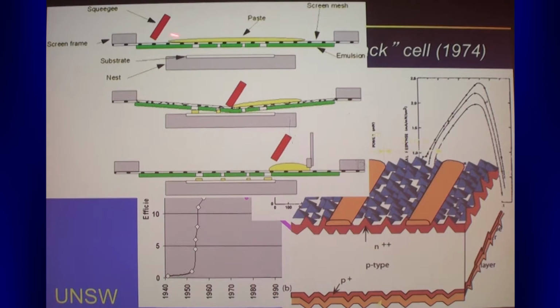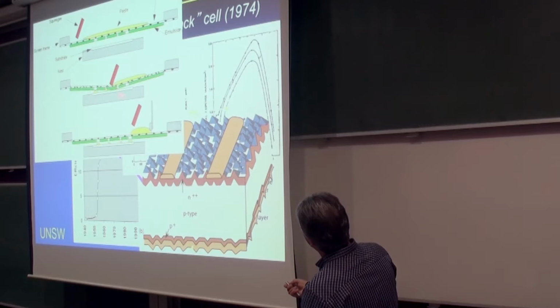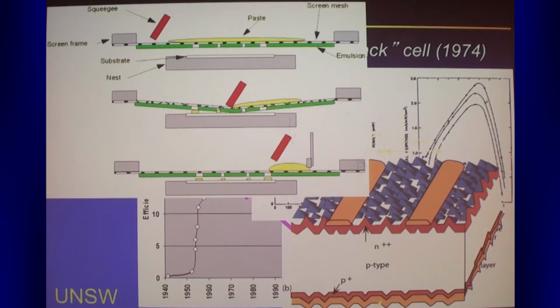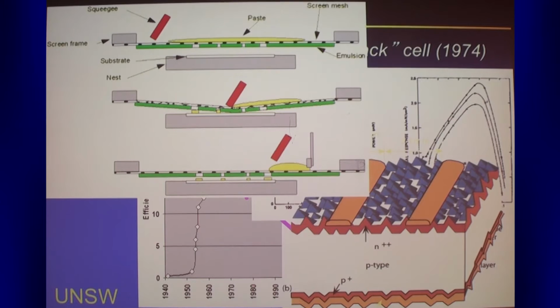You just have this screen and the metal is sort of ground up into a paste, mixed up with other stuff, so that it's a thickish type paste. And then it's just squeezed through this screen onto the cell to give you the defined patterns. The other technique I was talking about last lecture used a similar type of mask to this, but the metal was just sort of evaporated down here so that it just got through where the holes were, whereas this is more of a physical process where you push the paste through the mask. So this screen printing process works very well, and that's why cell technology has been dominant commercially for quite a while, because this screen printing is a really nice process that works quite well, and it's been improved quite a bit over recent years.